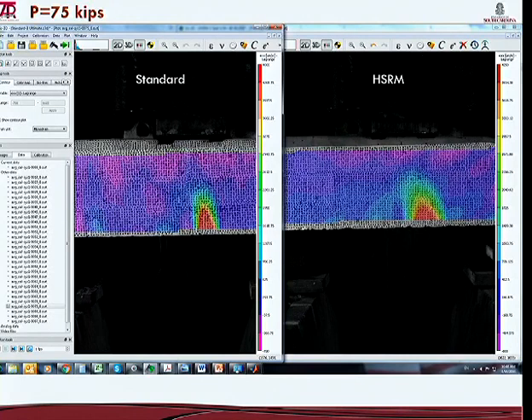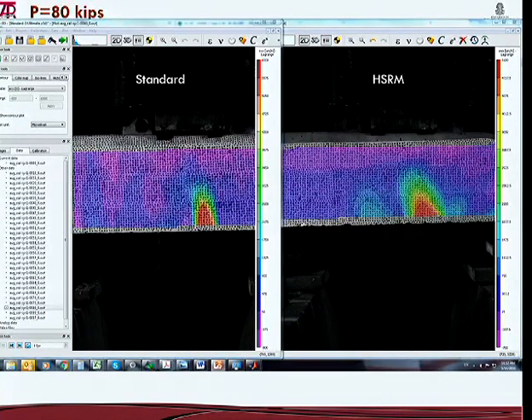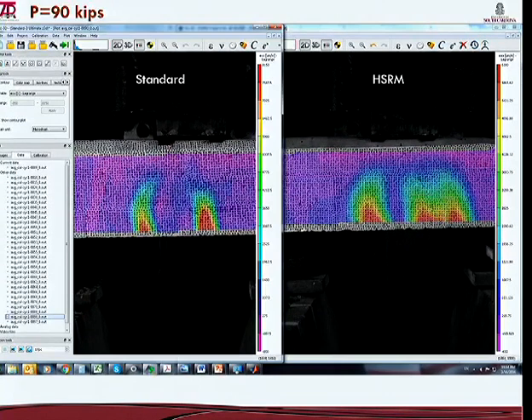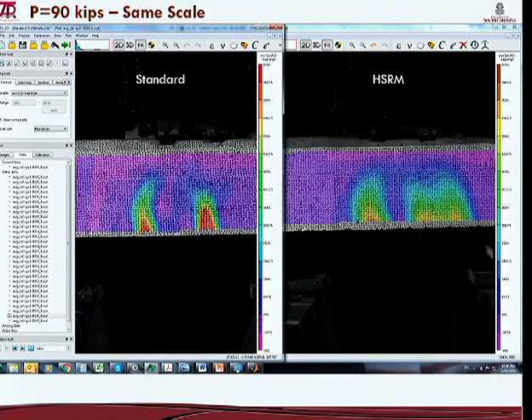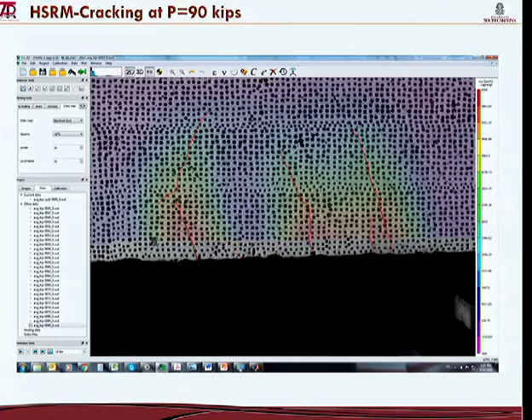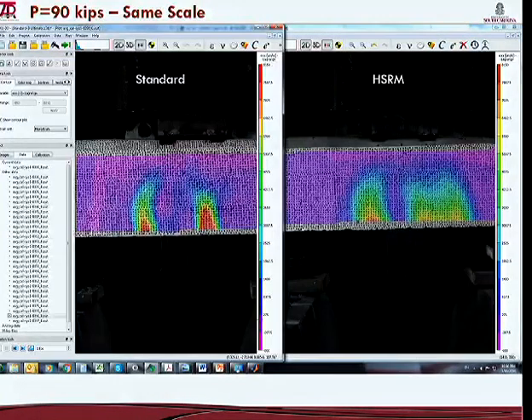As the load progresses, we see two very distinct cracks in the standard, multiple cracks in the HSRM. When we plot this to the same scale, notice the opening here is much higher than the HSRM. So this color map axis, going too fast there, were plotted to the same scale.